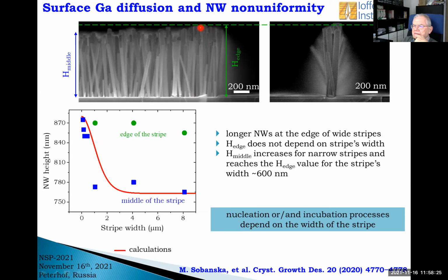This length of nanowires here remains the same. While here in the middle, at the beginning, nanowires are much shorter than at the edge, and then their length increases. So later on, right here, we get uniform length of nanowires. Okay, question is what's going on here? And of course, again, gallium surface diffusion is our suspect. But question is at which stage this gallium diffusion takes place here?